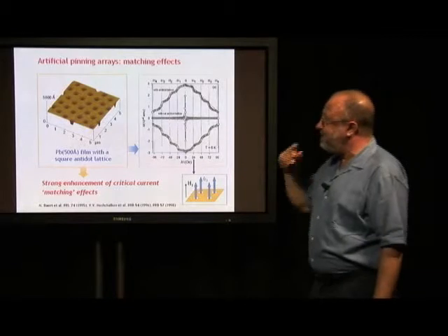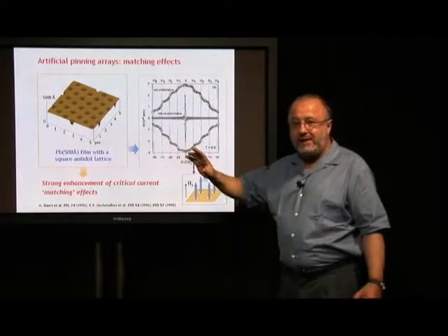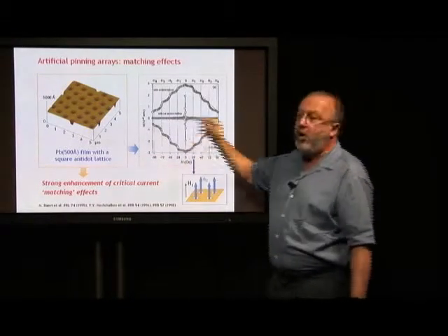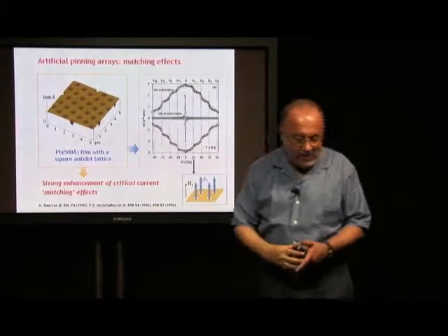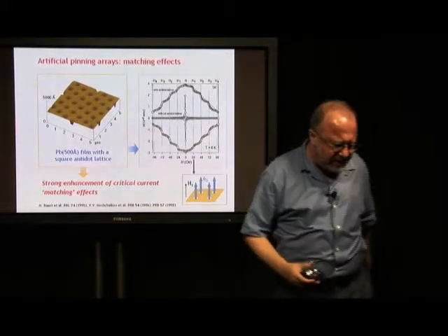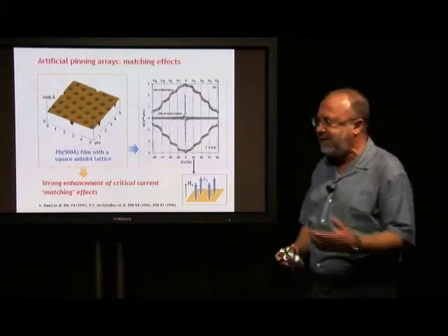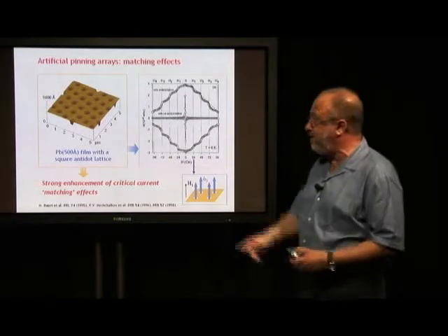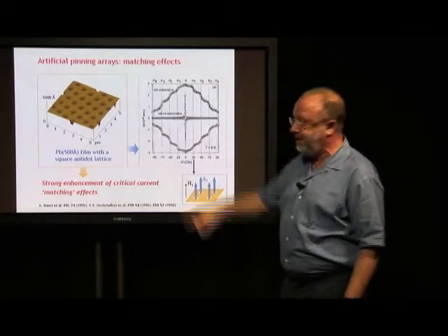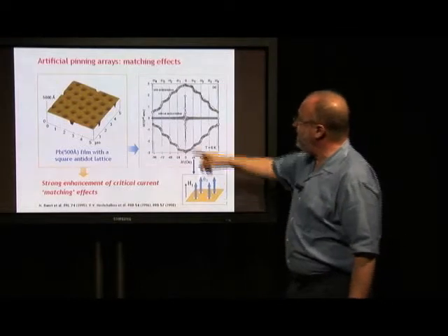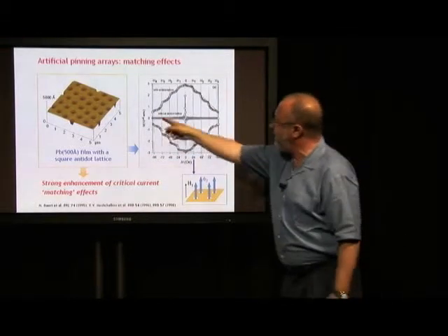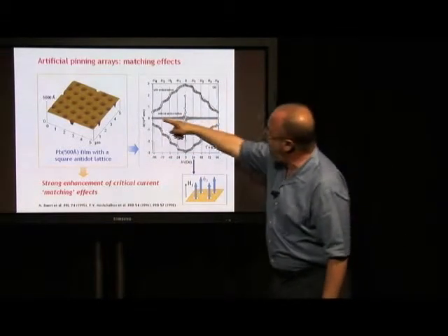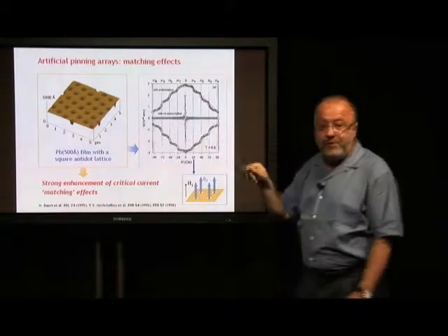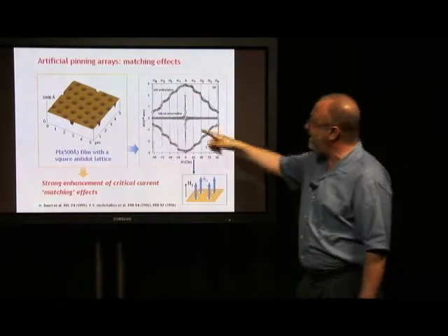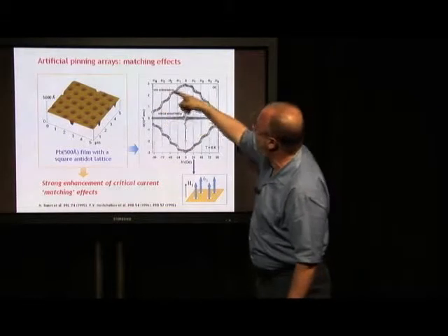Now, the interesting thing is what happens if you take the superconductor, like niobium, and you drill holes in it, for instance. This phenomenon was known for a while, but Professor Bruynseraede and his group revived this whole field. So there is a lead film with holes in it. If you measure the magnetization of this lead film as a function of field, you see a curve that looks like this. However, if you drill holes in it, instead of seeing a curve that looks like this, the curve looks like this, see? This.